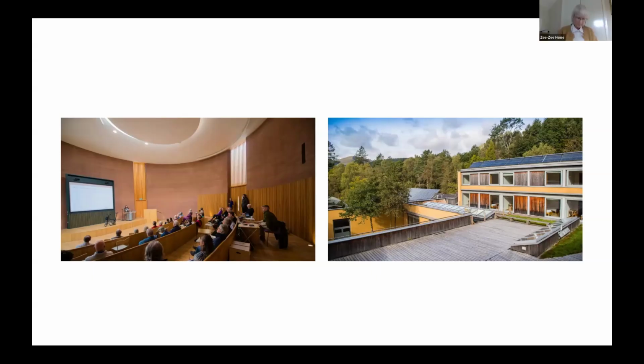Now they did also add 15% cement, and they did also use cement in the foundations. The Centre for Alternative Technology, being on the former slate quarry, had sufficient low-grade slate aggregate on site to make the building site level, but they made the foundations of ordinary concrete reinforced with steel to achieve the required strength and stiffness to withstand the movement of the underlying ground. They said concrete made from lime, not cement, or even unreinforced concrete would not have been suitable. But they did drastically reduce the embodied carbon by making the concrete from half cement and half ground up blast furnace slag, one of the things that Simon mentioned.